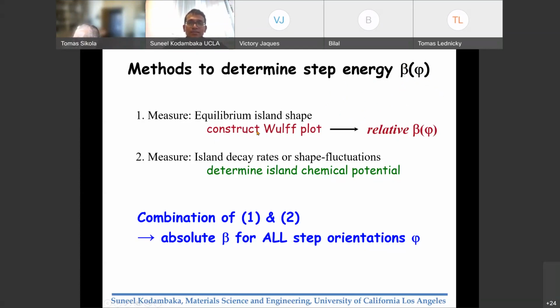In three-dimensional crystals, you're probably familiar with the so-called Wulff plot. This is a polar representation of the surface energies as a function of orientation. One can do the same for two-dimensional islands on surfaces, and have a polar representation of the step energies as a function of step orientation. The Wulff theorem tells us that one can determine the equilibrium island shape from the Wulff plot. But it gives you only the relative changes, so we need to be able to determine the step energies quantitatively.